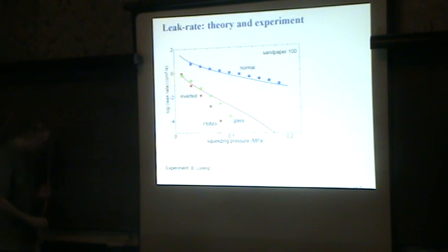Now we've done a second experiment. We took our sandpaper, which has this kind of surface roughness, and then we cross-linked silicone rubber against it, and then we removed it, and we get a rubber surface which has the opposite roughness of the sandpaper, the inverted roughness of the sandpaper. And then we put that in contact now with a smooth surface, not with a rough surface, but with a smooth surface. We have the same contact geometry as originally, but with inverted roughness.